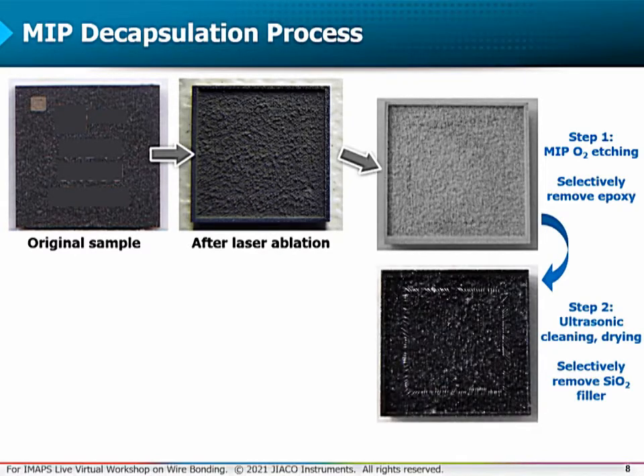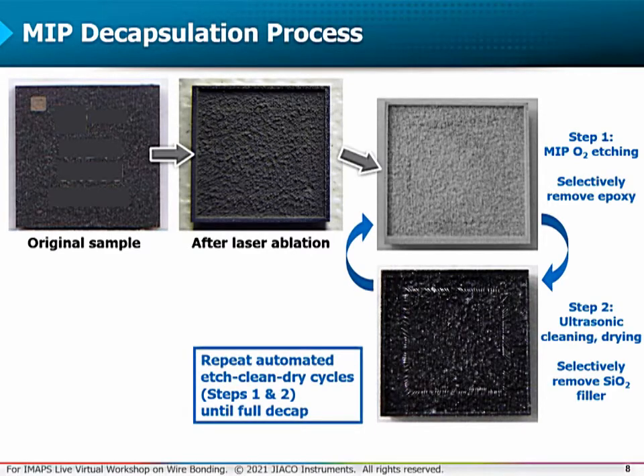Furthermore, the device is then automatically transferred into an ultrasonic bath with DI water, and the cleaning process will selectively remove silica fillers and expose a fresh layer of mold compound to be further etched. The device is then dried and automatically transferred back for an etching step. These steps 1 and 2 are repeated sequentially in cycles until the device is fully decapped.